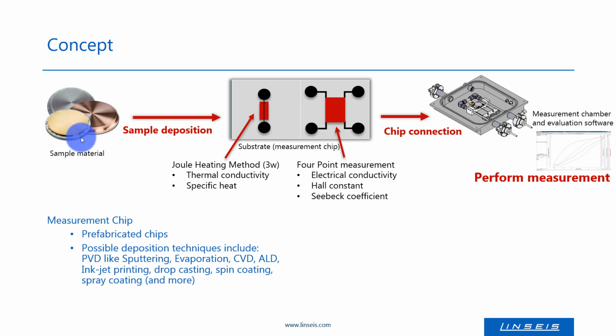The sample gets deposited on the pre-structured measurement chip. There are two main structures on the chip: a hot wire setup in order to characterize the thermal transport properties, as well as a 4-point configuration, which allows to characterize the electrical parameters.